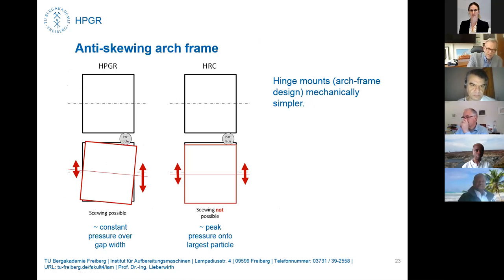This has to be kept in mind in designing also the machines. For instance, when I saw that new design, this HRC with this arch frame, it was even advertised that skewing of the rolls is not possible there. I found these people might not have understood the real operation of a confined bed system, because there you want to have the same pressure on all the particles. If you avoid the skewing, and if you have one big particle, that big particle gets the full pressure of the rolls, and all the other particles get nothing, in the worst case. So that's why at least a certain skewing should be allowed to achieve a good confined bed comminution.